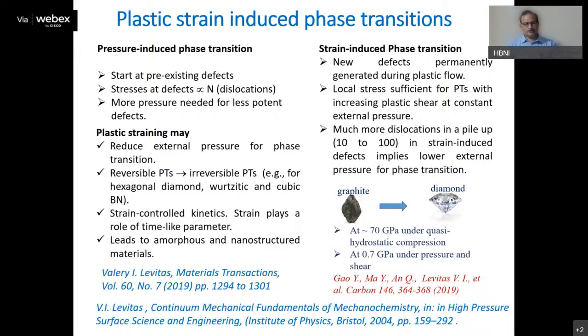So, what is the difference between pressure-induced and plastic strain? As we discussed just recently, these high-pressure phase transitions basically happen with very small movement of the atoms. Mostly, they are displacive. Now, it is very much similar to the martensitic kind of phase transitions. And we know that martensitic phase transitions actually start at some nucleation sites. There are some defects which act as stress concentrators. There are some locations where, when you apply pressure, they become more potent. They actually initiate the phase transition. So you get a nucleus of the martensite and then it grows as you increase pressure.